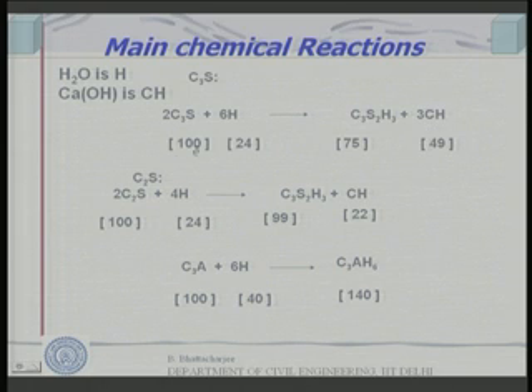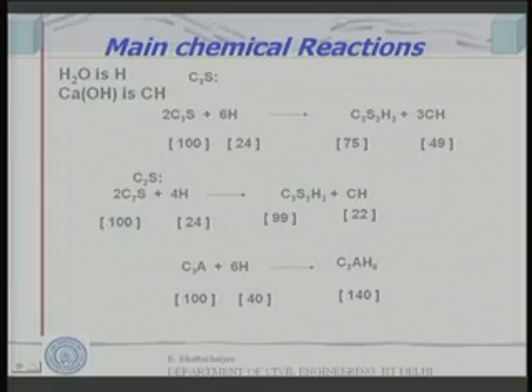In fact, 100 grams of C3S would react with approximately 23 or 24 grams of water, forming about 75 grams of CSH gel, calcium silicate hydrates, and 49 grams of calcium hydroxide, which is the same compound, same composition as slaked lime. So, the lime is formed.